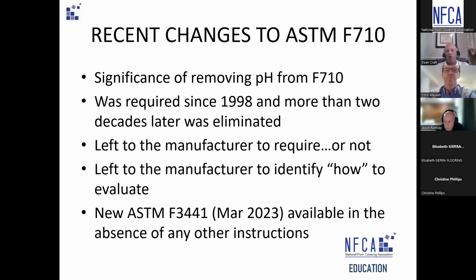Always before, the drop of water was just willy-nilly put on the concrete, let sit 60 seconds, and then you test the water. Well, there's this big assumption in that. The assumption is that the water's pH is 7.0. Well, there's plenty of literature out there that shows that water exposed to the ambient environment will absorb carbon dioxide and become more and more acidic over time. So it's quite possible that your water actually has a pH of 6, not 7.